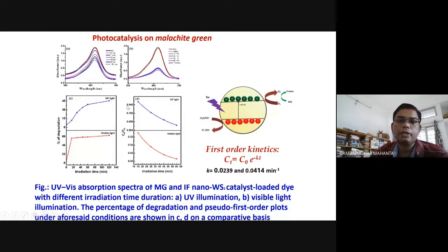In case of this particular material, what we found is that not under UV, but under daylight condition, under visible light illumination, the degradation was faster. That is what I wanted to show here, because otherwise photocatalysis is a very simple activity, and photocatalysis and photoluminescence are two opposite features of nanoparticles, all of us know. On the A side, you see 613 or so is the absorbance peak of malachite green, and the absorption value reduces with time in the presence of our photocatalyst, which is inorganic fullerene type WS2. The right hand side is under daylight illumination.